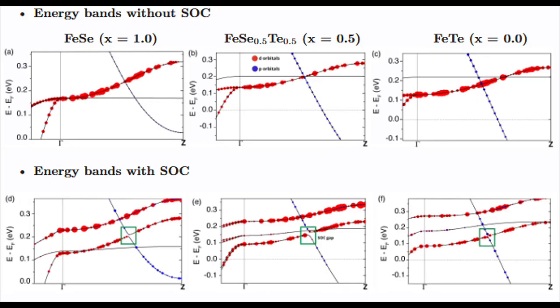Next, our results are presented in the following graphs. Electronic band structure in the gamma zeta path of the compounds iron selenium, iron selenium sub 0.5 tellurium sub 0.5, and iron tellurium is shown with and without spin-orbit coupling effects. The red circles indicate the weight of the d orbitals in the bands, while the blue circles show the contribution of the p orbitals. Adding spin-orbit coupling effects to the calculations induces energy gaps between bands, as indicated by the green square. The value of this gap is